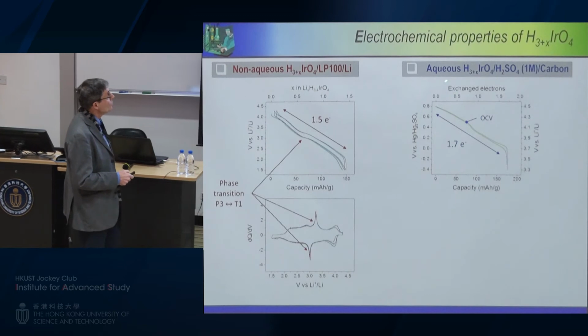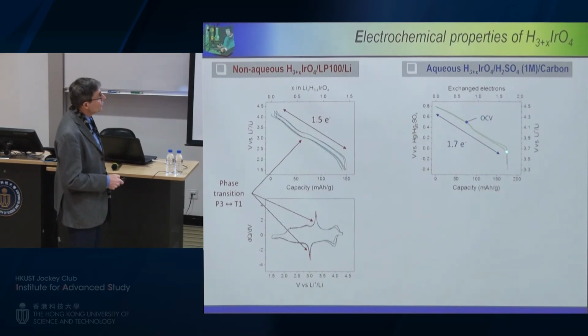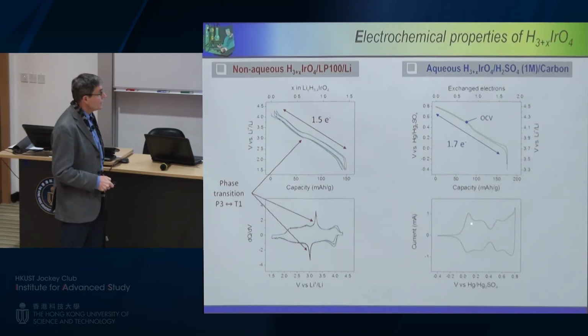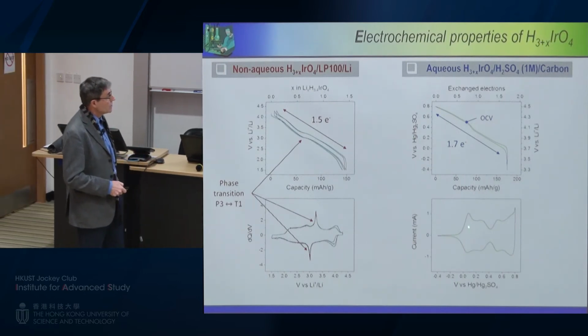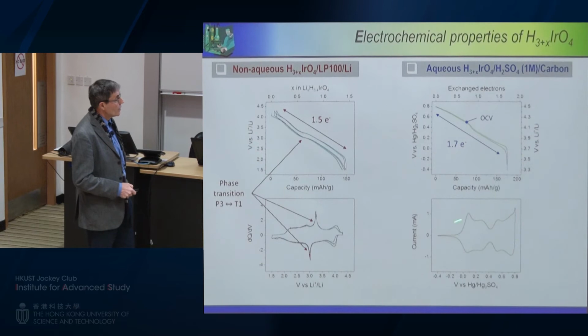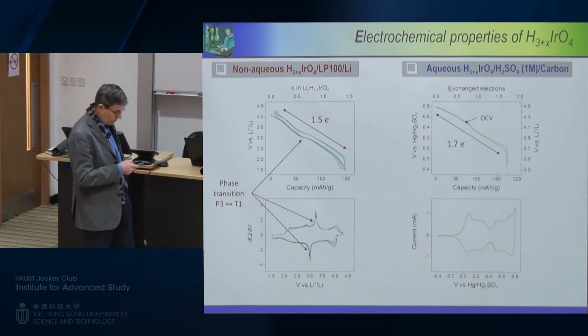And indeed, look what we obtain in the case of proton. We don't have any polarization anymore. So it means here you have an energy efficiency of 99%. And if you look at the derivative curve, as you can see here, we have a nice derivative curve, and we are able here to get 5,000 cycles.